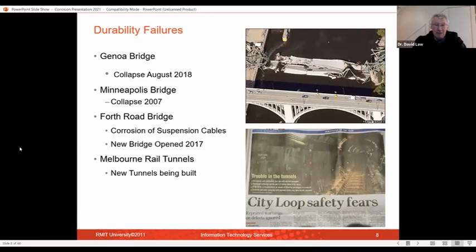So why are we particularly interested in corrosion? Well, in the extreme cases, we can have major failures. You may remember the Genoa Bridge that collapsed a couple of years ago, when there were a number of fatalities. And there have been other collapses, the Minneapolis Bridge about 10 years earlier. And we have issues with the Forth Road Bridge, where I used to be in Edinburgh. Major corrosion of the suspension cables led to having to construct a new bridge, which was opened in 2017, because of the potential disruption if that bridge was shut and there was perhaps a 50-mile detour required.